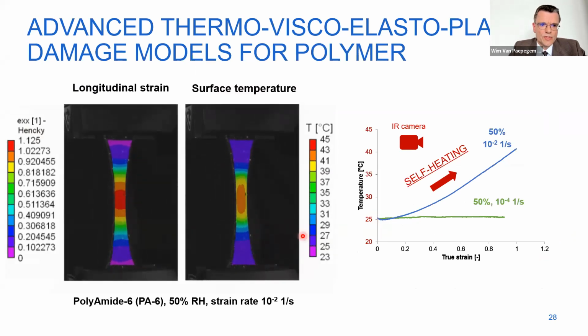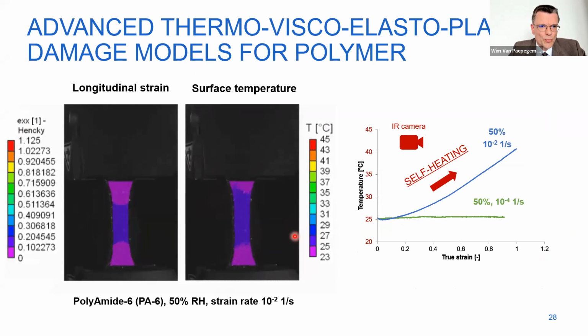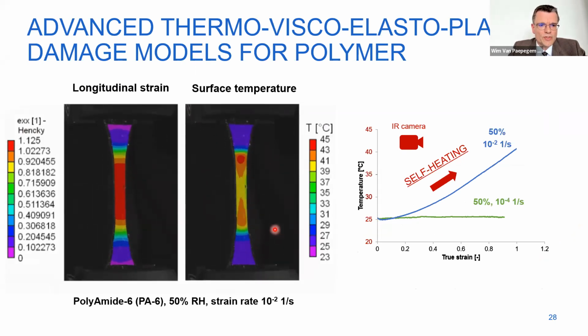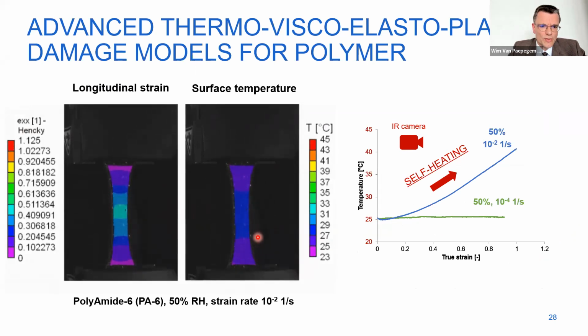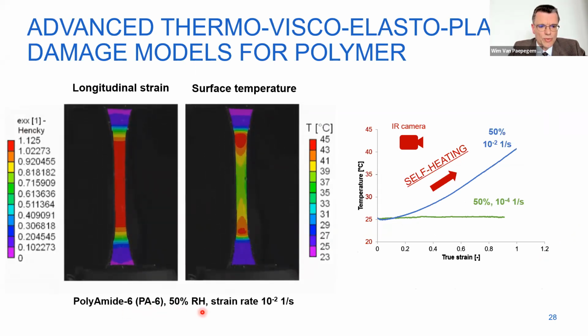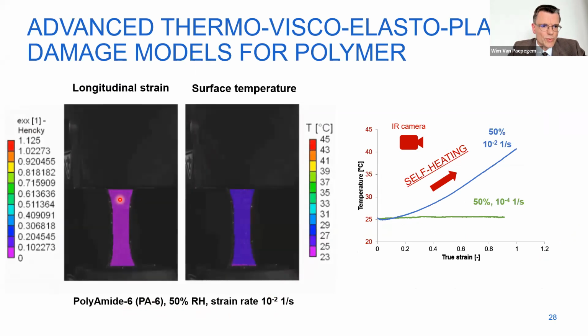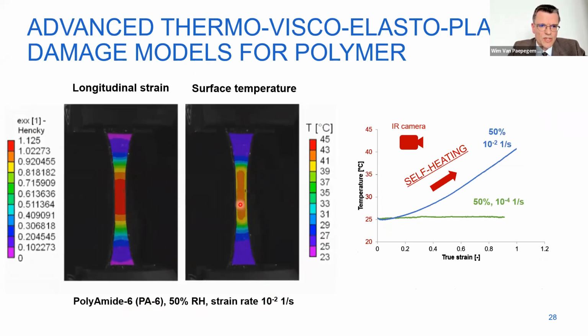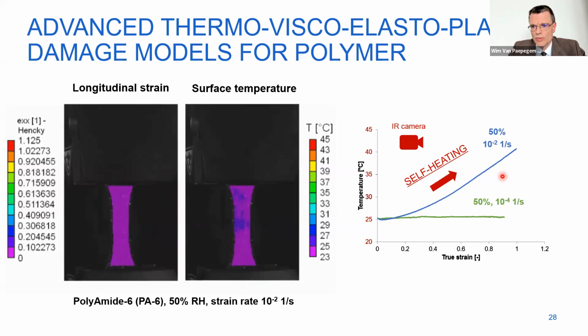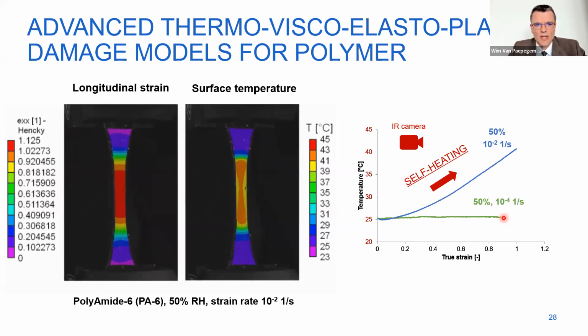Another thing, this is really about the polymer, because on the micro scale, your polymer is an individual ingredient. This is about this thermomechanical behavior. So here you see pure polyamide 6, 50% relative humidity, relatively large strain rate. And the left is the longitudinal strain, and the right is with infrared camera, the surface temperature. We synchronize them, and we also map the temperature on the deformed shape. And then you see that indeed we have self-heating. So at this strain rate, the temperature rises quite a lot. And at a lower strain rate, 2 decades lower, the temperature stays just at ambient temperature.